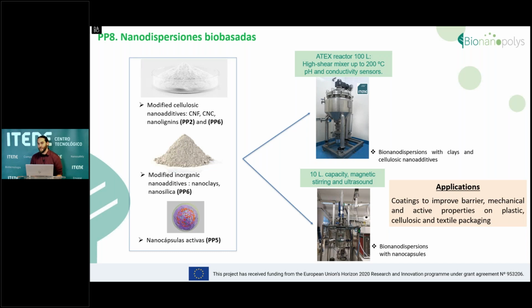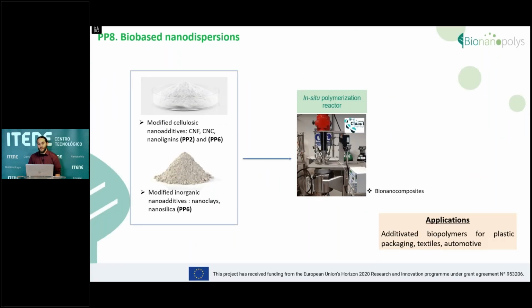And lastly, some of the additives could be applied as a nano dispersion in liquid media, for instance, for coatings. So by collecting the nanocapsules, the modified cellulose or the clays, we can disperse them in aqueous or solvent-based coatings with our reactors and then apply it as a coating. One of the things we can do as well is in situ polymerization in the reactors of our partner CIDAUT, which allows us to generate better dispersion in some cases and to have the polymerization of some biopolymers directly on top of the nano additives that then will be carried on as a suspension.